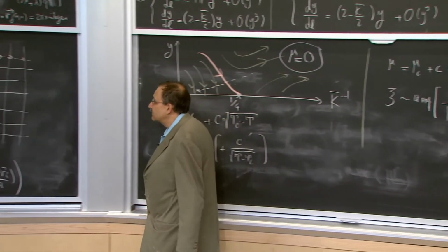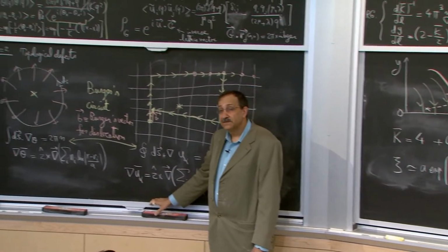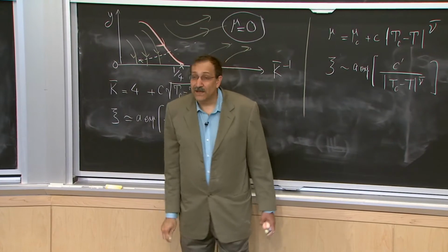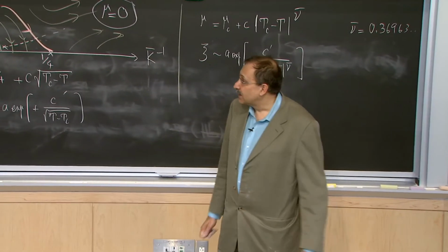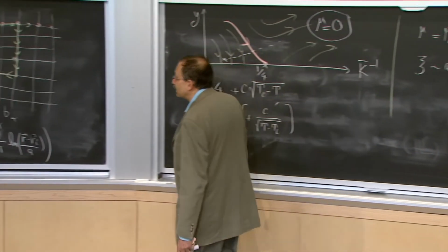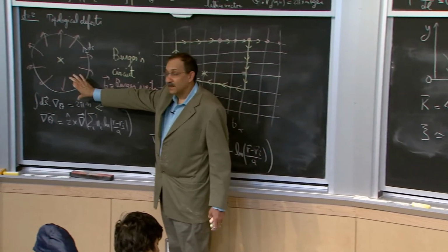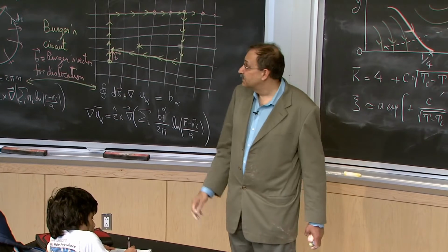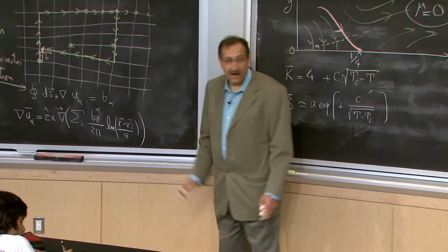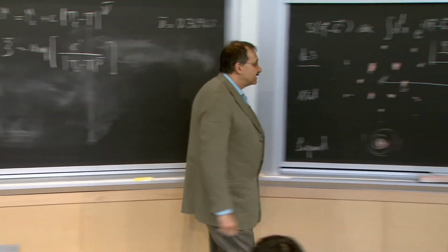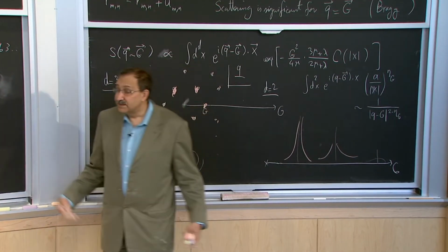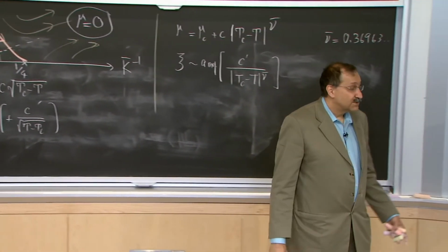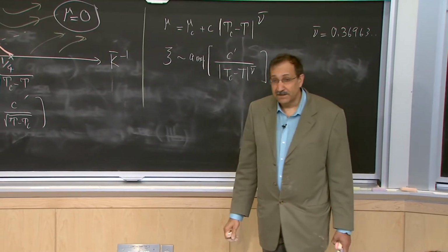So once people understood the original Kosterlitz-Thouless transition, it was a very natural next step for them to think about dislocations in a two-dimensional solid and say that in the same manner that the unbinding of these defects got rid of the residual long-range order that was left in the XY model, this kind of ordering that we said exists for the two-dimensional solid disappears as a result of unbinding of dislocations, and you get a liquid. Okay? Turns out that that's not correct.